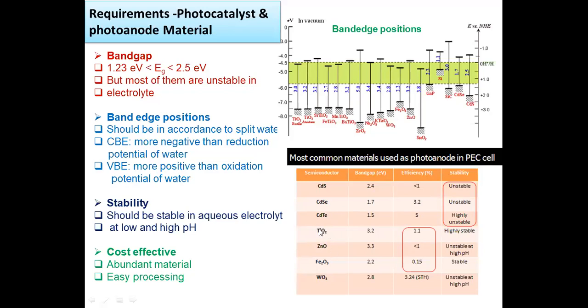On the contrary, if you talk about TiO2, it is a very stable photocatalyst, but if you look at the band gap, it is very large. So sunlight cannot break this. Sunlight cannot be useful here, and you need UV light to do this job, which is practically not what we want. So if we have to talk about what can be appropriate among existing materials, CdS, okay, is unstable, but you need to work on it to make it stable. Then maybe TiO2, how you can tune its band gap, that is one scope.